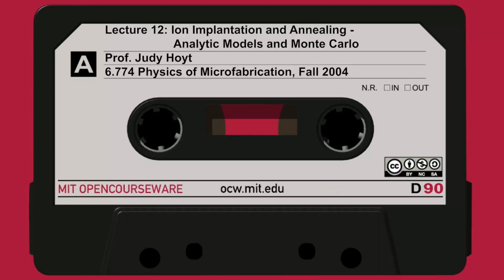So what I want is this concentration C star at this point to be less than some background concentration, whatever it might be. Let's say your wafer is doped 10 to the 14th per cubic centimeter. You want to make sure that the concentration profile in the mask is such that by the time the profile gets to the edge of the mask, it's down below 10 to the 14th, so you really can't see it. That means you have a good mask. You've designed it to be thick enough. If it's thinner, then you get too much of the species implanted into the wafer itself. It's not a good mask.